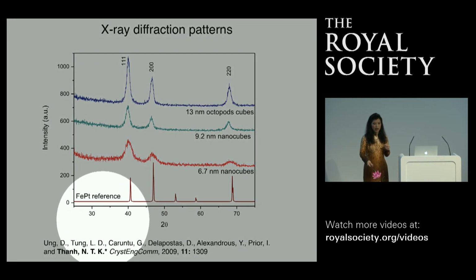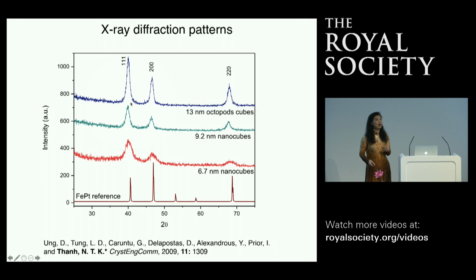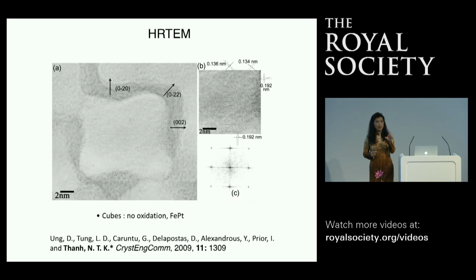So basically, you have a reference, and then you can see what your particle's composition is. But also, the width of the peak allows you to calculate the size of the particle. By TEM you can also determine the size of the particle, but the difference is that XRD allows you to look at a lot more sample than the TEM, where you can only look at a few hundred particles at the same time.